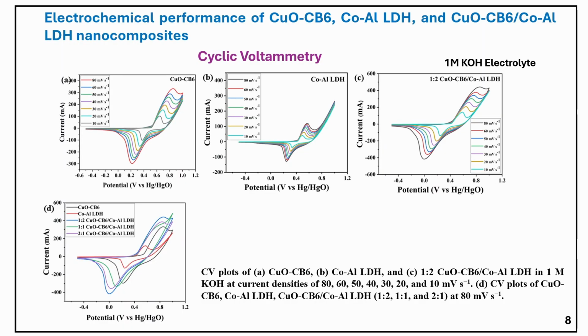Next, coming to the electrochemical performance of CuO-CB6, cobalt aluminum LDH and nanocomposite. So first is cyclic voltammetry. The electrochemical behavior of the synthesized materials was examined using cyclic voltammetry. The CV plots for cobalt aluminum LDH, CuO-CB6 and 1:2 nanocomposite displayed distinct redox peaks in a 1 molar KOH electrolyte at varying scan rates from 10 to 80 millivolt per second within the voltage range of minus 0.5 volt to plus 1 volt.